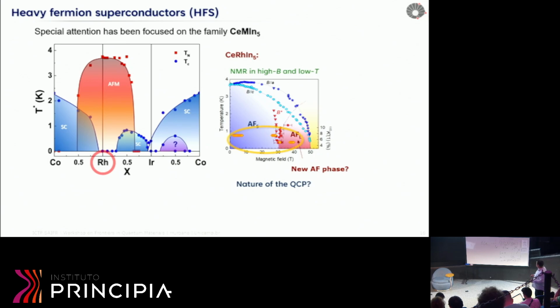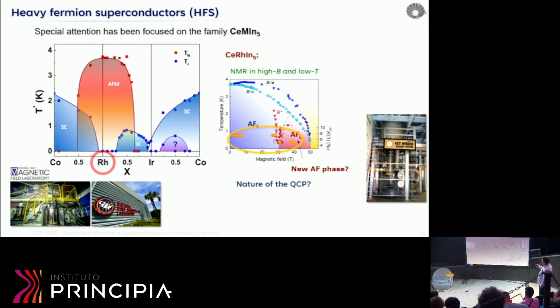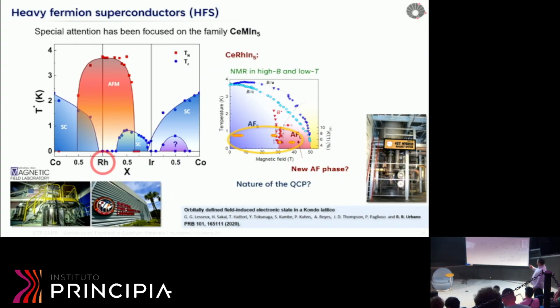So we actually tried to understand this scenario, doing NMR, and by measuring these materials in the hybrid system in Tallahassee, we could contribute to this scenario, providing some microscopic evidence. That was the first microscopic evidence for this anomaly in this phase diagram. And I should say that this scenario found basis also for CeIn3. People in Los Alamos were investigating the nematic phase, even in the CeIn3 system.